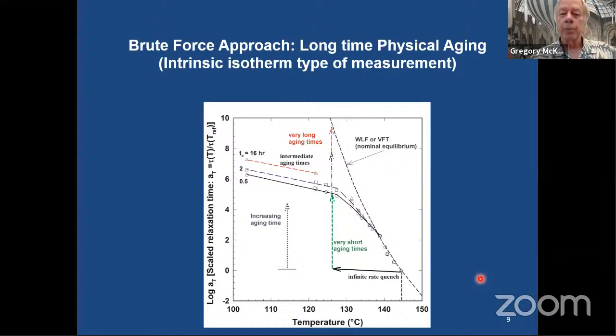So the brute force approach, long time physical aging. As I said, it's an intrinsic isotherm type of measurement. These are data from long time ago from polycarbonate, where here's the VFT extrapolation to the equilibrium data. And here's aging data, and you can see it falls over. Actually, these data are close to equilibrium, and you can see they're not actually quite getting to the VFT extrapolation. So there's a question there. But at that time, we didn't recognize it. But here's the typical aging behavior.